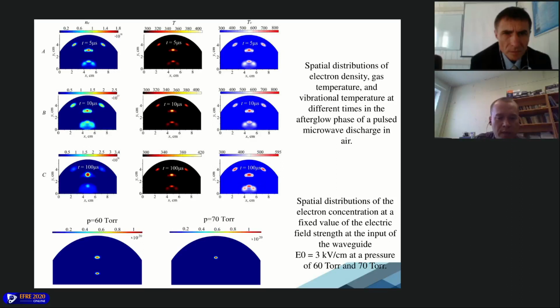And here we can see the spatial distribution of the electron density at a fixed value of electric field strength at the input of the waveguide, and pressures of 60 and 70 torr. We can see two plasmoids formed, and when the pressure is equal to 70 torr, we can see only one plasmoid formed in the numerical region.